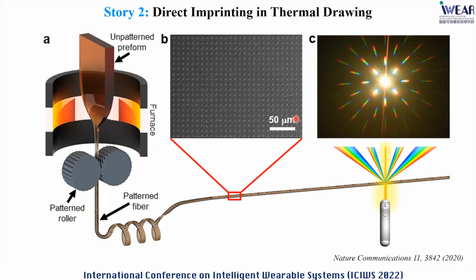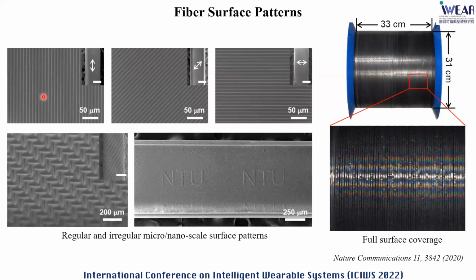So here, for example, we demonstrated that we will be able to print those two-dimensional dots on the surface. And if we shine the light, we see this beautiful diffraction pattern, indicating the high quality of those surface structures. Then further, we demonstrate, for example, we can also imprint those one-dimensional grooves along the fiber, perpendicular to the fiber, or along a certain angle to the fiber axis. We'll be able to print those two-dimensional patterns with different heights on the outer surface of the fiber. And here is more interesting: we can even print very complicated patterns, for example, the NTU three letters all over the surface of the fiber.